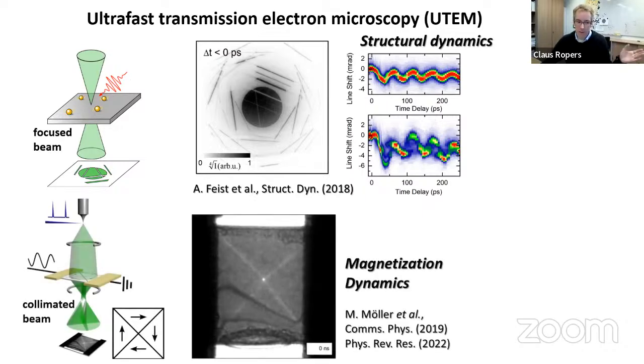Okay, another very different example, which also works with the same optical excitation of the tip, the same production of electron pulses, but a different sample excitation is shown down here, because we can not only use electron or optical excitation of the sample, but we can also drive currents through a sample in a way that is synchronized to the electron beam. And in this way, basically, if you can see this here, you have laser pulses on the tip, and here we've synchronized a radio frequency current passing through a permalloy thin disk.